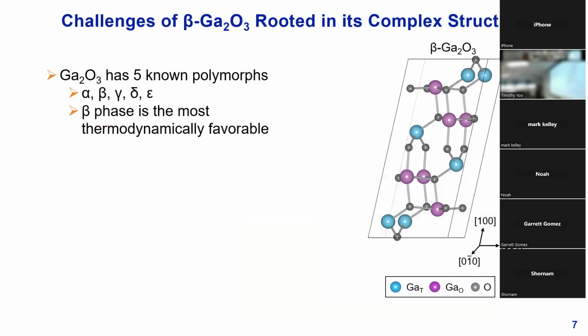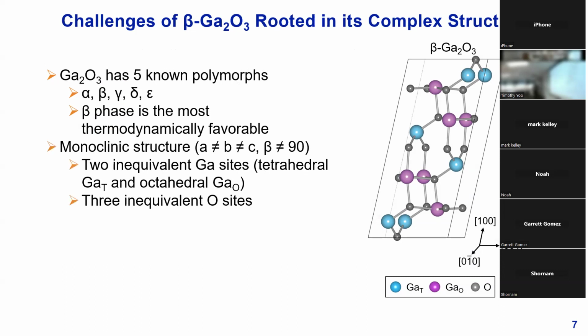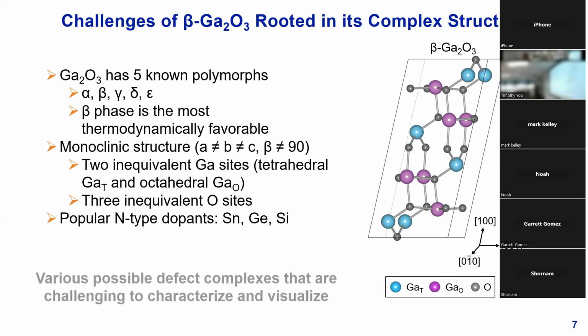A lot of the challenges with characterizing the beta gallium oxide structure historically have been rooted in its complex structure. Gallium oxide has 5 known polymorphs, with the beta phase being the most thermodynamically stable. This beta phase has a monoclinic structure, 2 inequivalent gallium sites, and 3 inequivalent oxygen sites. And if you add in the fact that there are several different types of n-type dopants that are popular these days in literature, like tin, germanium, and silicon, there are a lot of different possible defect complexes that you might encounter that are going to be hard to both characterize and visualize.